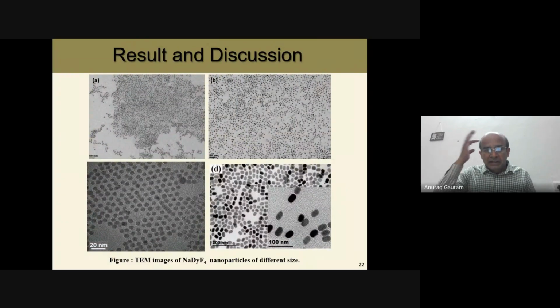So these are the particles prepared. We prepared the same particle for different sizes. We prepared sodium dysprosium fluoride nanoparticles, like here 5 nanometer, this 10 nanometer, and here 20 nanometer around, or maybe slightly 15 nanometer. They are longer here. So 5, 10, and 15. They are capsule shaped, so they have different aspect ratios. They are very hard to control sometimes, but we can prepare different sizes, and we can measure all these results with XRD to check whether they are those particles or not.